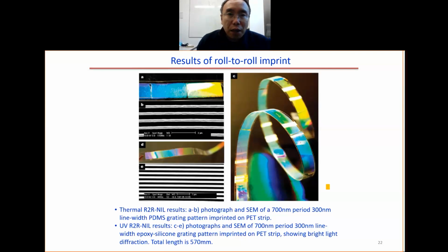So here are the images done by the roll-to-roll imprint. A and B are done by the thermal roll-to-roll imprint using the PDMS grating mold imprinted into the PET strap. C, D, and E are done by the UV roll-to-roll imprint. In this case, the mold is made of an epoxy silicone grating pattern imprinted into the PET strap. The grating area here has a 700 nanometer pitch. You see it's colorful. We will see later on why it is colorful. This is called roll-to-roll imprint, which gives you a very high throughput.